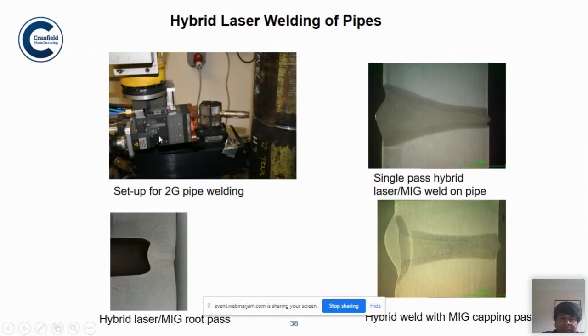So this is a study that was done. This is for the root pass welding, and these two macros on the right are showing a single pass hybrid laser/MIG. This is almost 12.5 to 13 millimeter, and you can see you can create a complete proper weld in a couple of passes. Whereas if you just use MIG, it will take like 10 passes to create such a structure. So the productivity is improved by miles, basically.